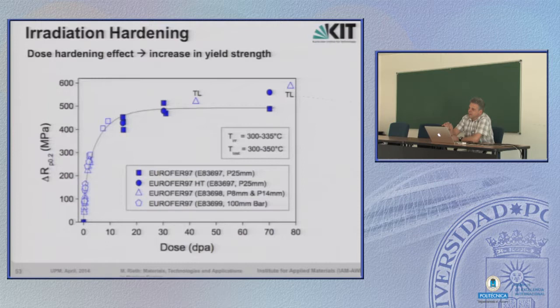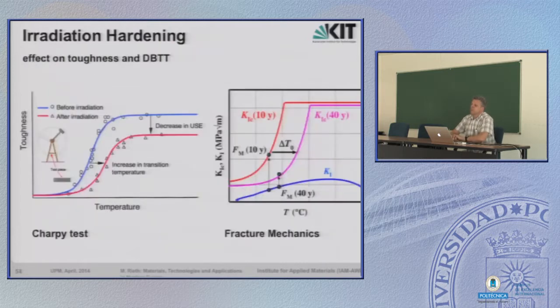What we have done with tensile properties, I show you now for Charpy test or fracture mechanics. In principle, the same happens in the Charpy properties. We expect or we observe an increase of the ductile to brittle transition temperature because the material embrittles due to the hardening, but also toughness goes down a little bit due to the irradiation defects. The same can be seen in fracture mechanics studies. DBTT is shifted to higher temperatures because the material embrittles.